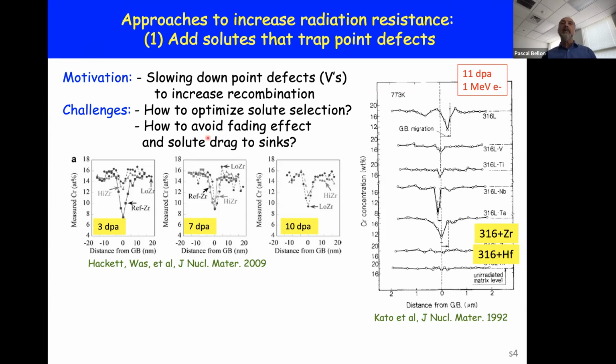their kinetics. There are some examples that have been demonstrated in the 70s and in the 1990s by Kato and his co-workers, where they added oversized impurities such as zirconium and hafnium in 316 stainless steel, and demonstrated using 1 MeV electron irradiation that in those materials doped with impurities, the traditional radiation damage of chromium depletion at a grain boundary in a standard 316 stainless steel does not take place if one has doped the material with these impurities that hopefully trap point defects. It's complicated because that effect is only transient; it fades away.